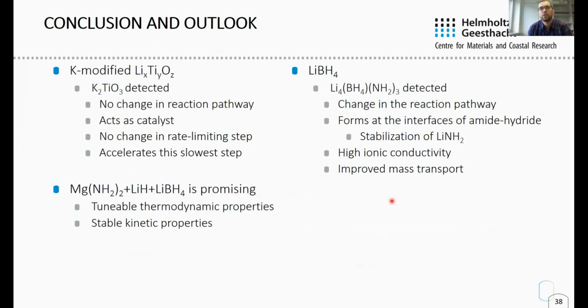As a conclusion, in the system with titanate additive, I detected potassium titanium oxide, and it doesn't change the reaction pathway. It acts as a catalyst. It doesn't change the rate limiting step, but it accelerates this step both in hydrogen absorption and desorption. In the system with lithium borohydride additive, I detected Li4BN3H10, which changed the reaction pathway. This forms at the interfaces of amide hydride particles and stabilizes the intermediate product lithium amide. The presence of this highly ionic conductive additive may improve the mass transport properties.